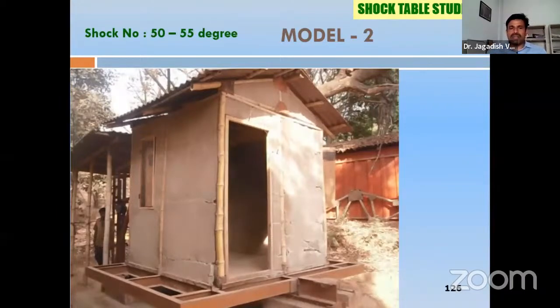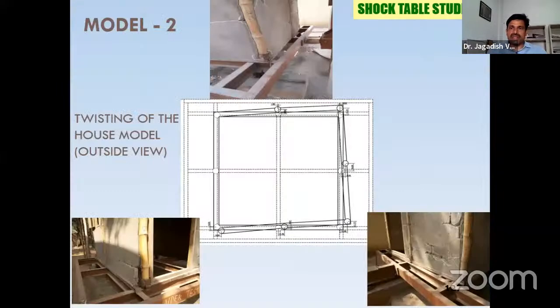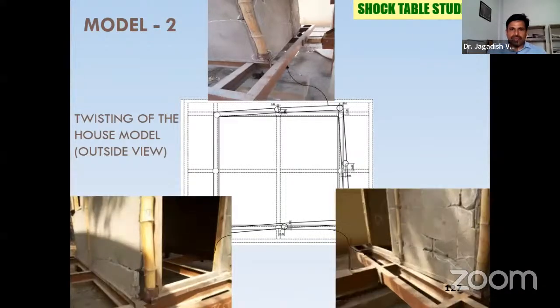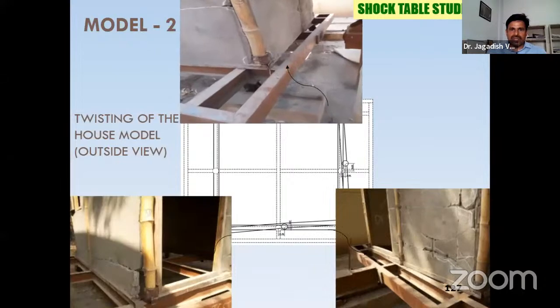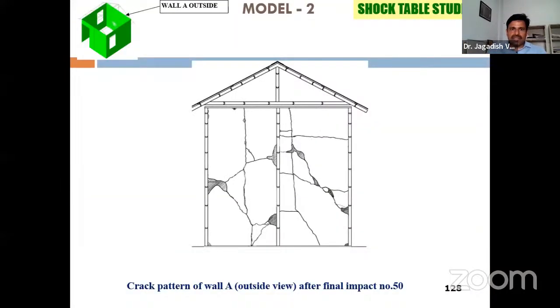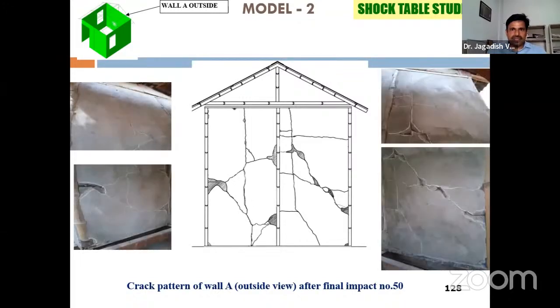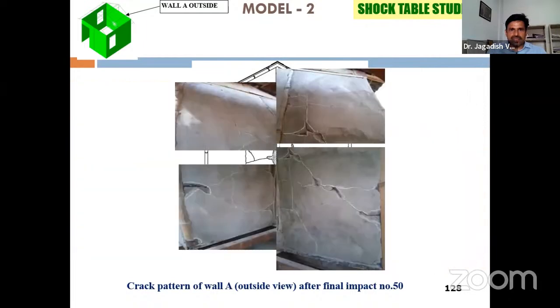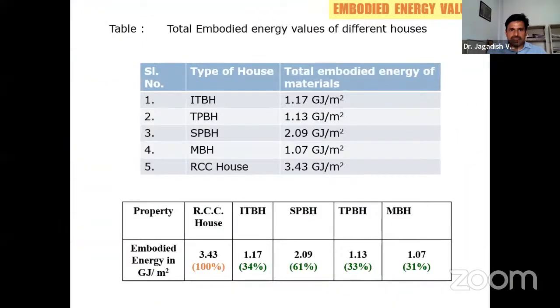In a real case, there was no major debris falling from the house, and there was no major damage you can observe here. This is almost 50 shocks at higher intensity. You can observe the twisting of the house model. This is the outside view of the building. These are the final crack patterns of the wall at impact number 50. You can see the cracks.